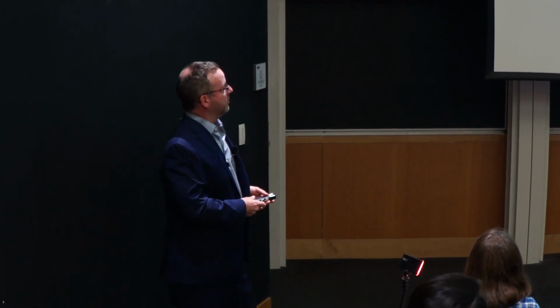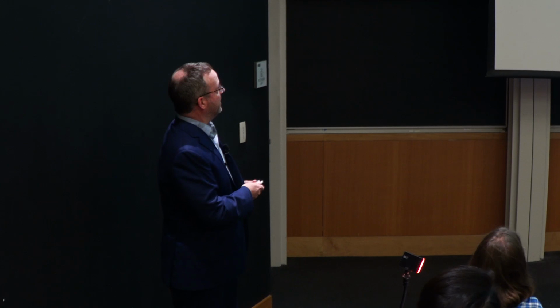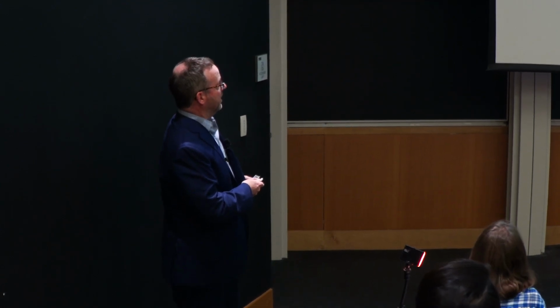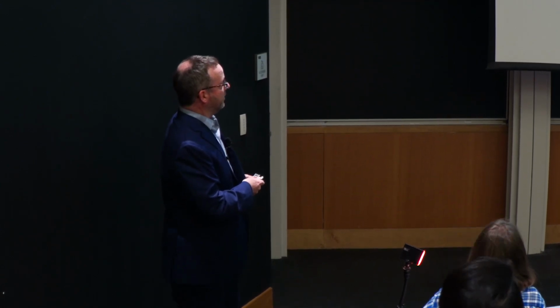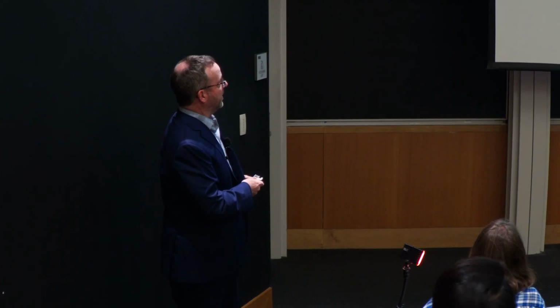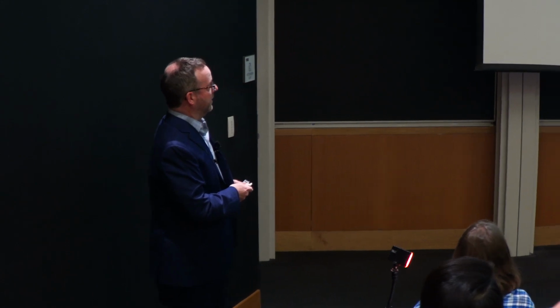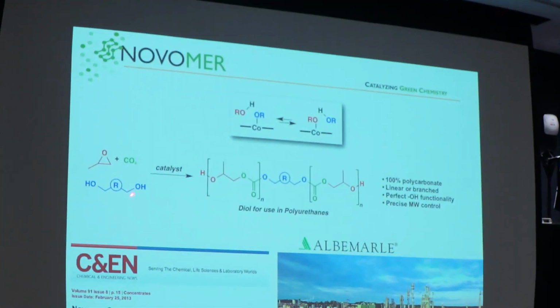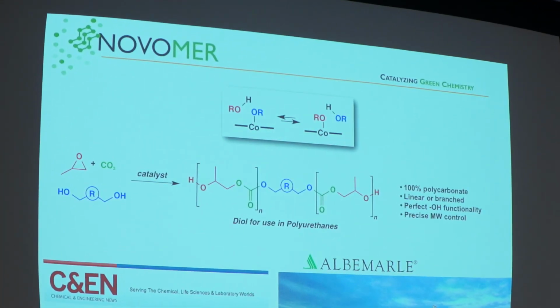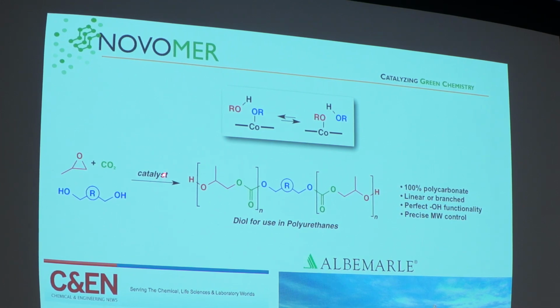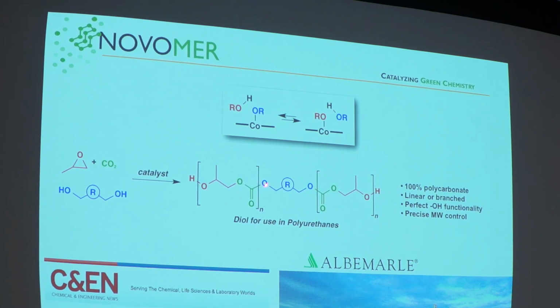So I'm going to really simplify what we did. The idea was to develop a catalyst that allows an alcoholysis reaction. If we're growing a polymer chain off our cobalt, we need an alcohol that can come in and react, and now this alcohol can grow a chain while this one's dormant. If this process is really fast, the idea is that we start out with a diol. You can also start with a triol or a tetraol if you want to make higher functionality polymers. We add in our catalyst, and when the catalyst activates the alcohol, we grow the polypropylene carbonate.